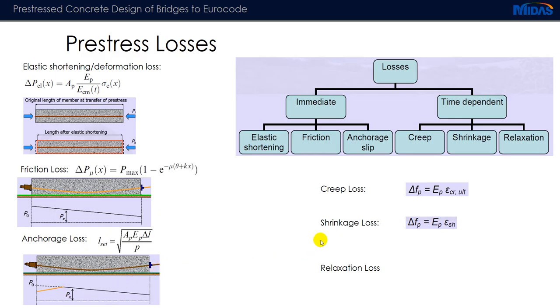For time-dependent losses, there is creep loss, which is because of the deformation of concrete. Concrete may shorten or elongate, and along with it, it will change the length of the pre-stressing steel, which will lead to loss of pre-stressing forces. Similarly, shrinkage loss will lead to shrinkage in concrete as well as the shortening of the strand, and correspondingly the pre-stressing stresses will be lost. Relaxation loss is similar to the creep behavior in concrete, but this happens in steel. So if steel is stressed for a longer time, it will be affected by relaxation loss, and that has to be also considered in our pre-stress loss analysis.